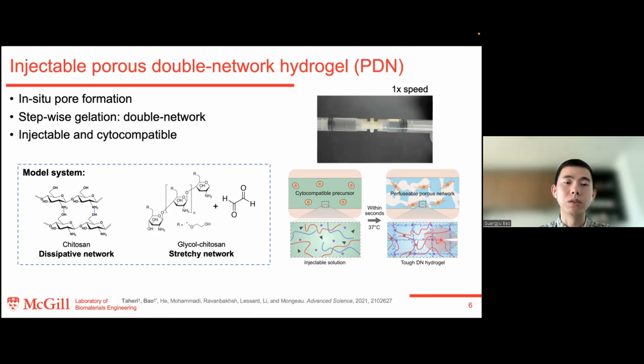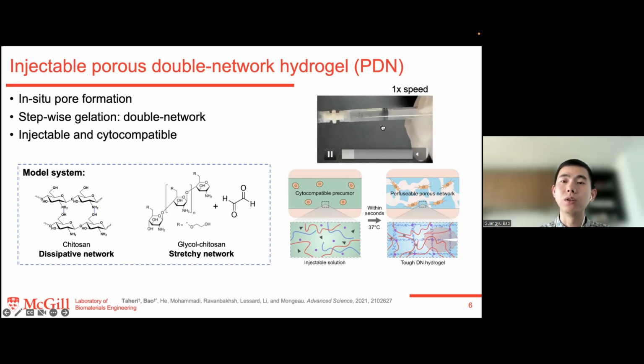And we aim to improve the delivery method and the mechanical stability of the resulting hydrogel while maintaining its cytocompatibility and also porous nature. So to achieve this goal, in addition to the chitosan, we have introduced a second polymer, the glycochitosan, to the polymer solution to reinforce the hydrogel through a double network design. And we mix the two polymers. We first put the polymer solution in one syringe and the cross-linkers in another syringe. And by mixing those two solutions, the pH of the mixture is neutralized. At this stage, we can mix the cells inside and inject it into the human body.